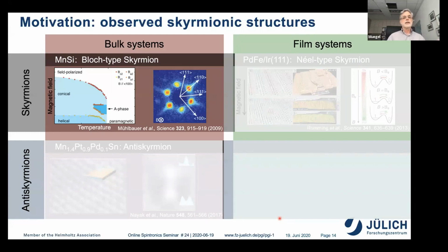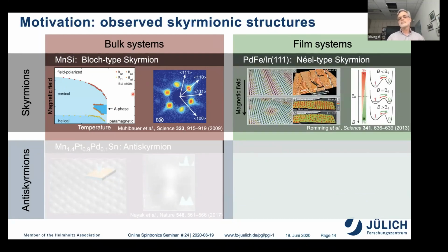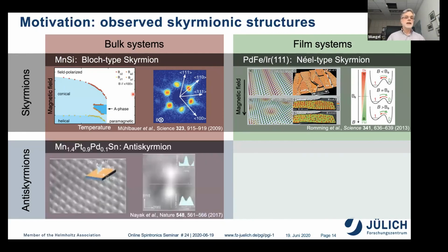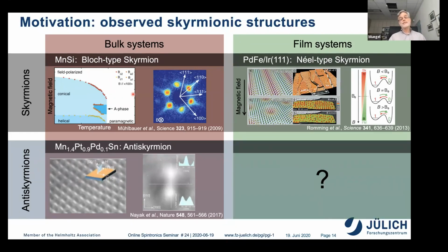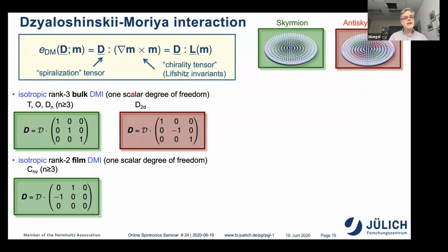So basically we have the bulk systems, and a very famous one is the B20 systems, for example, manganese silicide, and they have the typical Bloch type skyrmions. Then we have the film systems, for example, palladium iron iridium. They typically have the Néel type skyrmions. And then we have the D2d materials, which exhibit antiskyrmions. And the question is, do we also have antiskyrmions in thin films? Not discovered yet.